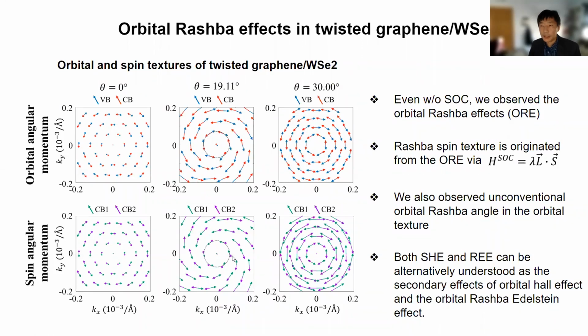Otherwise, it's forbidden. One way to understand this is, if you have a mirror plane, and a spin that is rotating in this manner, then with a mirror operation that spin is going to flip. Therefore, the spin cannot have an orientation that is along the mirror axis. If you don't have any mirror plane or mirror symmetry, then you basically can have any type of spin orientation.